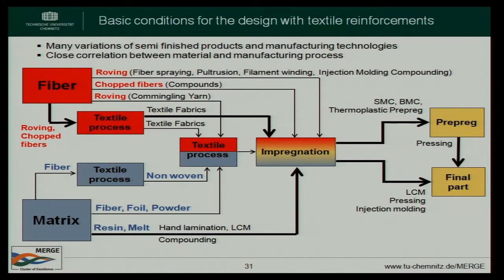So, for example, take a single fiber, you go to the roving. This is what you can normally buy from a fiber supplier, carbon fiber roving. You have some typical titers. You can use the roving directly for, let's say, fiber spraying, pultrusion, filament winding. You have to combine it with the matrix. You have different ways. Normally, wet impregnation means you have your resin or a thermoplastic melt. You can go directly over filament winding into impregnation, and you have your part.